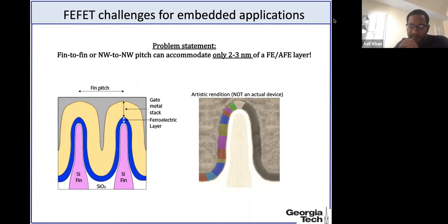So yeah, that's a very good question, and this is an open question. I don't think anyone knows the answer to it, but most of the work has been limited between 5 nanometer and 10 nanometer of thickness, and it's an empirical observation that below 4 nanometer there is a significant change in the microstructure, and basically any material below 3 nanometers, crystallizing them is really hard. For some reason, it just wants to be amorphous. It's not that you cannot do it, but the techniques that we use to crystallize it at 5 nanometer do not work at 2 nanometer. Either we need to increase the temperature, increase or decrease the annealing time, change the ambient gases that are present when crystallizing, and most importantly,